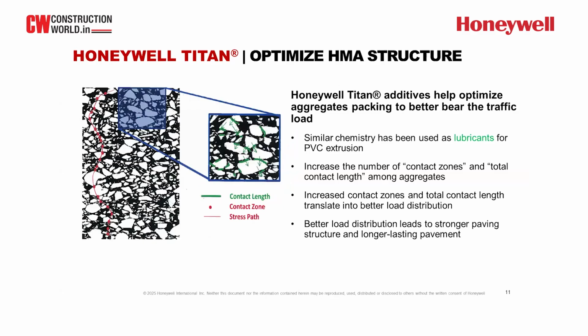So with the improved lubricity from Honeywell Titan in the PMB, what we found is this better lubricity will help to optimize the hot mix asphalt aggregate structure. To the left, these are two high resolution digital camera images we took on a couple of core samples compacted in our lab. We use a diamond saw to vertically cut the core sample into small pieces, around 1 centimeter in thickness. Then, you can see here, the white colored area are aggregate, right? With different size, you have a larger aggregate, you have a smaller aggregate. The black colored area are either bitumen or PMB or air voids.